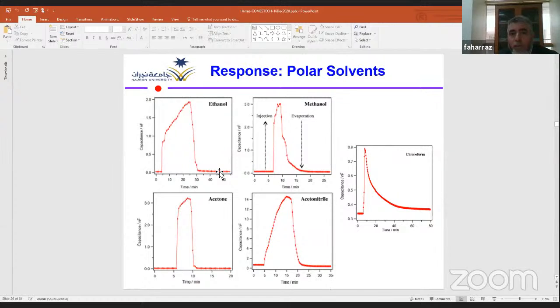Upon infiltration of some polar solvent into the nanoporous structure, using, for example, ethanol, methanol, acetone, acetonitrile, or chloroform, you can see a rapid increment of conductance as well as capacitance. You can measure this change upon infiltration. And once the porous layer is completely filled and wetted with the organic solvent, it reaches the maximum level. Then leave the device at room temperature, the organic solvent starts to evaporate, and the capacitance or conductance will return to its baseline again after the device is completely dried.